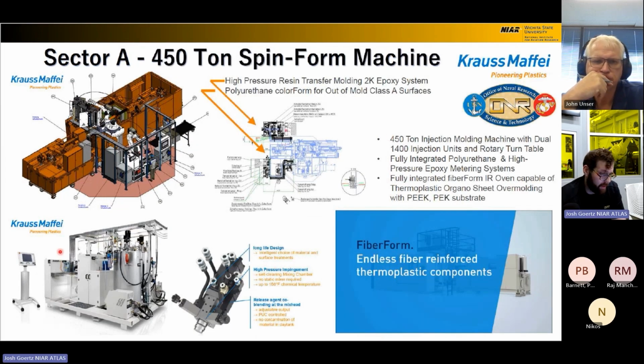And this is a second spin-form injection molding machine, which has a lot of the same technology with a couple of additions. This machine allows us to have 2 different molds where the central mold spins 180 degrees to expose it to 2 different cavities. So you can actually do multiple layers of injection molding. Or you can get a chop fiber structural reinforcement in one mold, or flip it around and expose it to